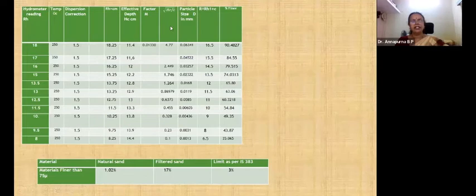Now this is the hydrometer test, which is done to find out the presence of finer particles in the sand. This was done with the help of Dr. Krishna sir from the Department of Civil Engineering, Bangalore University. He helped us to do this, and we have got this percentage of finer materials. From this, we observe that the filtered sand contains finer materials greater than 17%, whereas the limit as per IS 383 is 3%, and for natural sand it is 1.02%. This filtered sand is 17%, which is higher than the 3% limit.